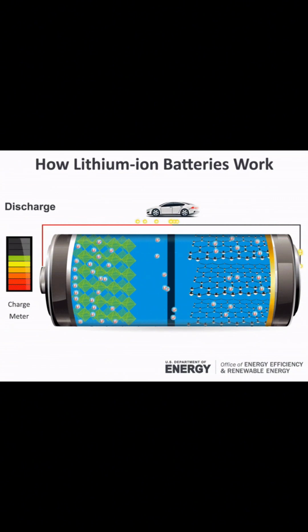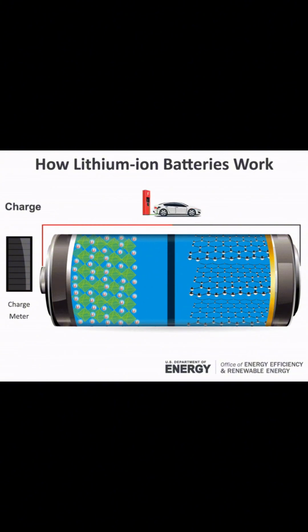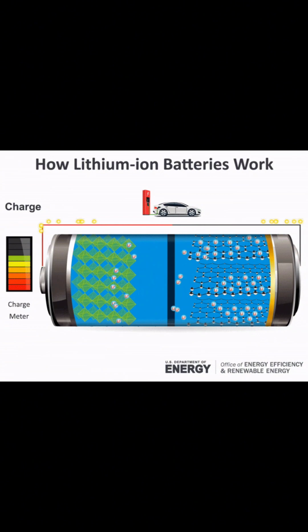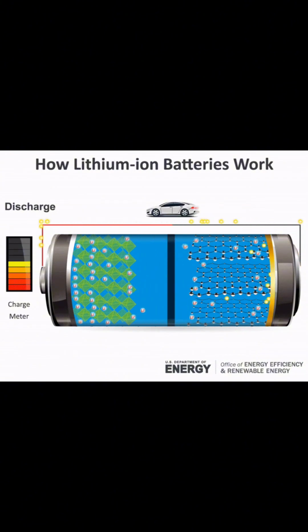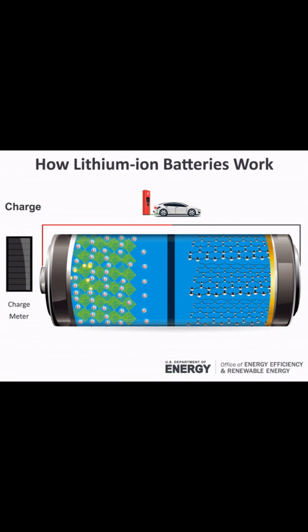In a study, scientists provided 3D imaging and model analysis to reveal the main cause, mechanics, and potential mitigations of the problematic degradation of the batteries over charge cycles. They found particle cracking increase and contact loss between particle and carbon binder domain are observed to correlate with the cell degradation, and indicates that the reaction heterogeneity within the thick cathode caused by the unbalanced electron conduction is the main cause of the battery degradation over cycling.